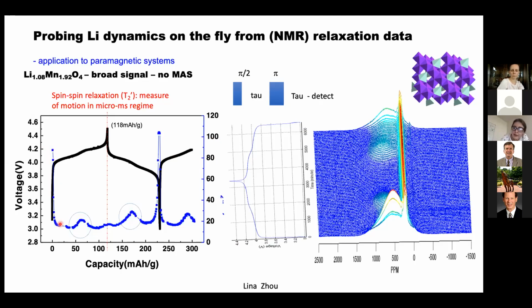That's very simply that you have a structure, it's stuffed full of lithium, you pull a few lithiums out, you have vacancies, and the mobility goes up. And so the T2 drops, and then when you hit this 0.5 composition, you form an ordered phase in the material where you can order lithium filled, empty, and the lithium slow down. So the T2s increase slightly, and that means that you see more signal, and that's why you get this apparent increase. Just by doing these relatively straightforward experiments, you can say something about the dynamics of the material on the fly.